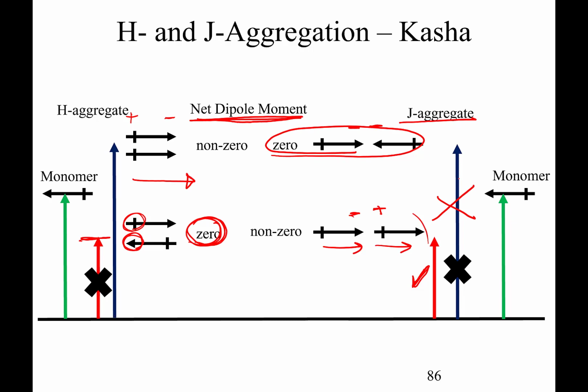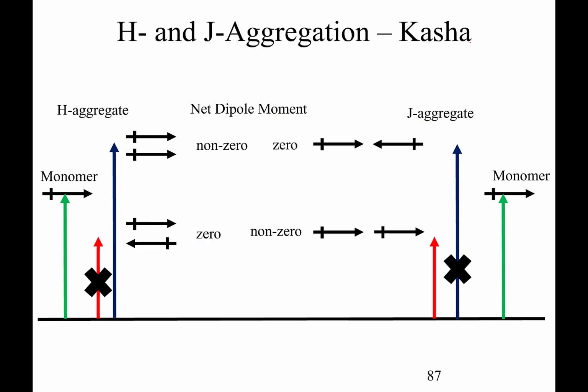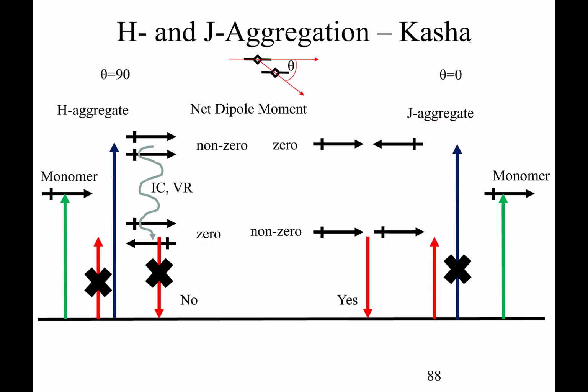So this is the typical understanding of the Kasha description of dipole-dipole interaction. We think that we always have vibrational relaxation or internal conversion from an excited state that's high. The states drop back down to the lowest energy state. In principle here there'd be no fluorescence, because that fluorescence wouldn't be allowed since we've got a zero net transition dipole moment. We would see fluorescence from the ground state of the J aggregate.